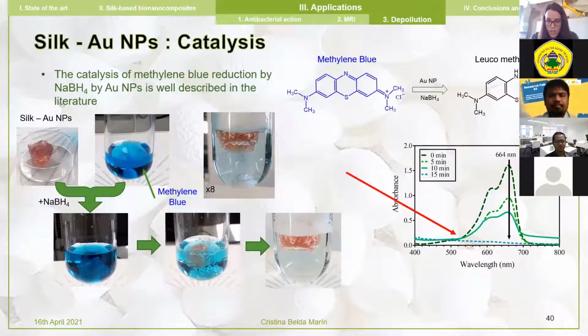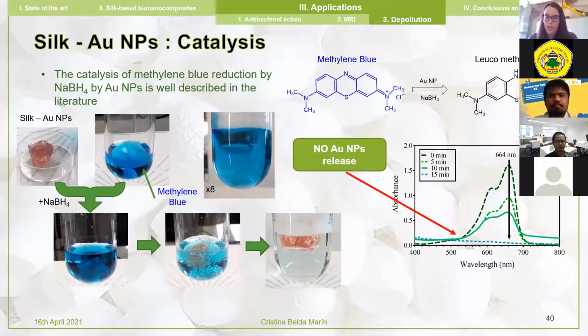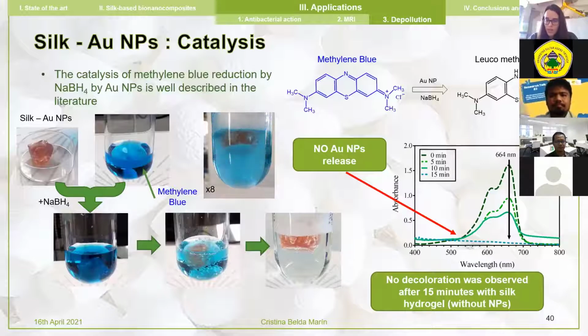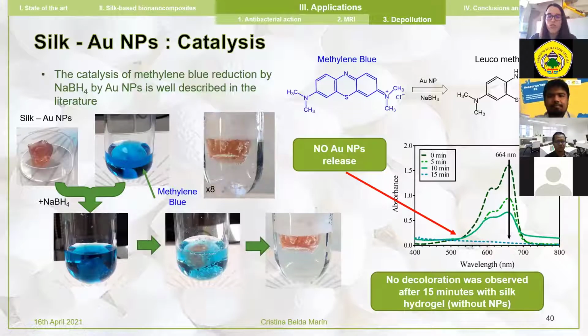Of course, it's important to notice that, if you remember, I told you that gold nanoparticles have a maximum absorbance at 520, and here it's not seen. So we can say that there is no release of nanoparticles into the solution, which is very important for us as well for toxicity issues that may appear. So within 15 minutes, our hydrogel is able to reduce the entire solution of methylene blue.